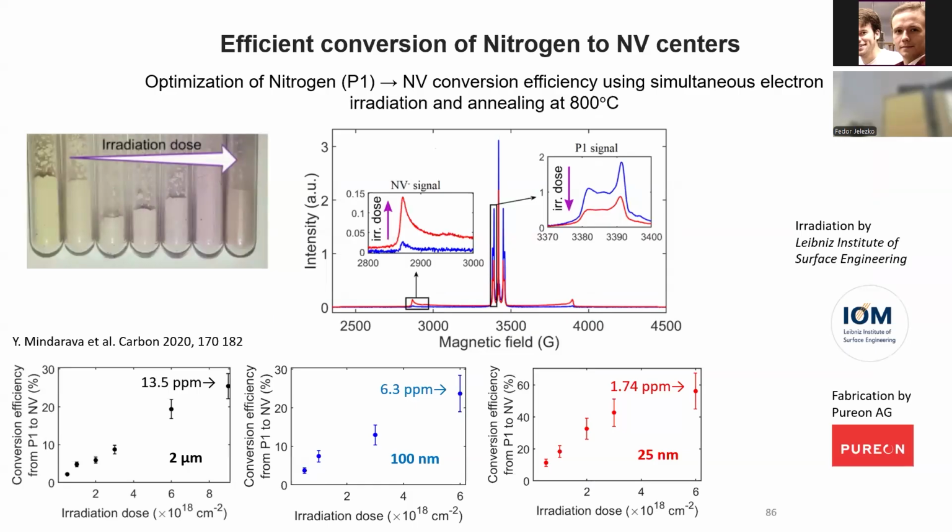Experiments with polarization of nanodiamonds are not so trivial, because in the tubes they have all possible orientations. So nice driving of NV centers with specific frequencies is challenging here, because the frequencies of nanodiamonds, this is the EPR spectrum, are spread over several gigahertz of frequency range. So we have to find new protocols allowing this polarization transfer for a very orientationally disordered system.